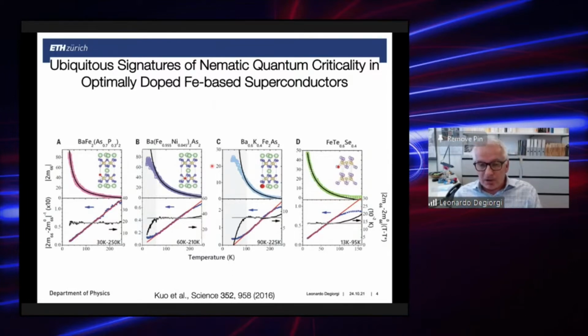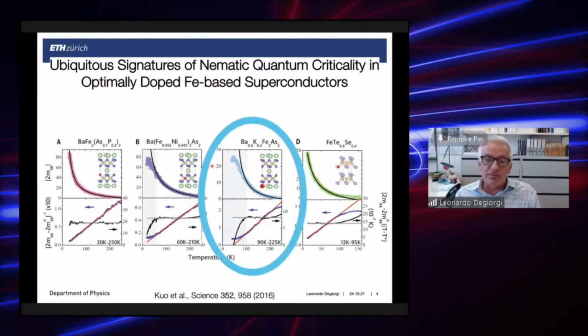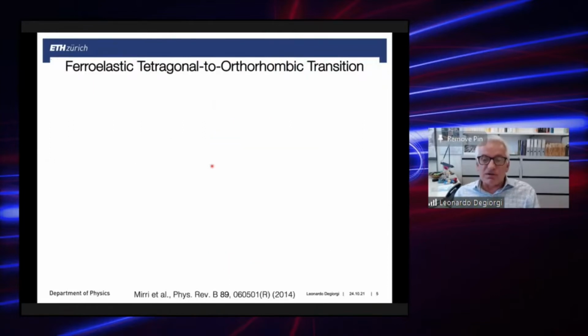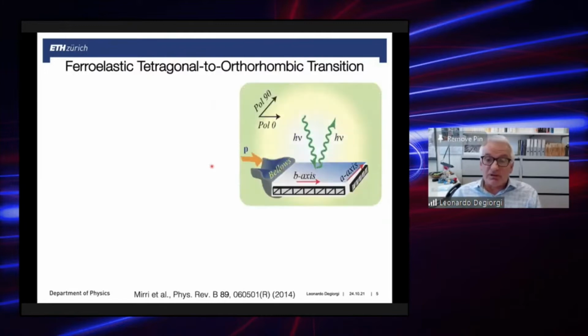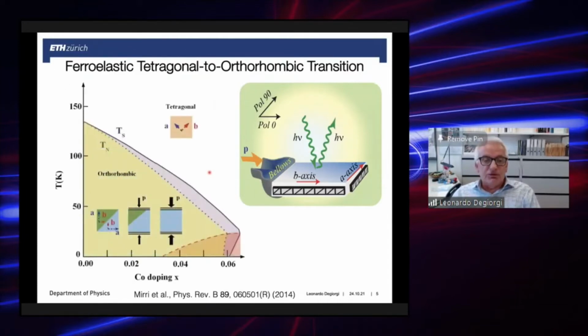Because of that, we focus our attention on these optimally doped materials with a Tc of 38 degrees Kelvin. Now, the experiment consists in measuring the optical reflectivity over a very broad frequency spectral range, which extends from the far infrared all the way up to the ultraviolet, and as a function of two tunable variables.